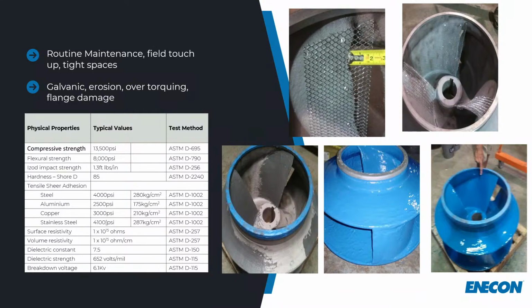What you see a lot of times when you see coating failure, wherever you're at in infrastructure, you're bonded at a rate where corrosion just gets underneath and busts it out. Usually that's around 2100, 2200 PSI. The coating is only bonded at, let's say, 1400 PSI. The math works out where it's just going to bust out.